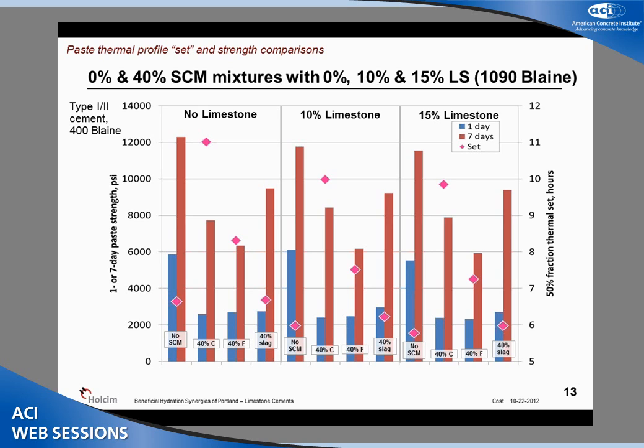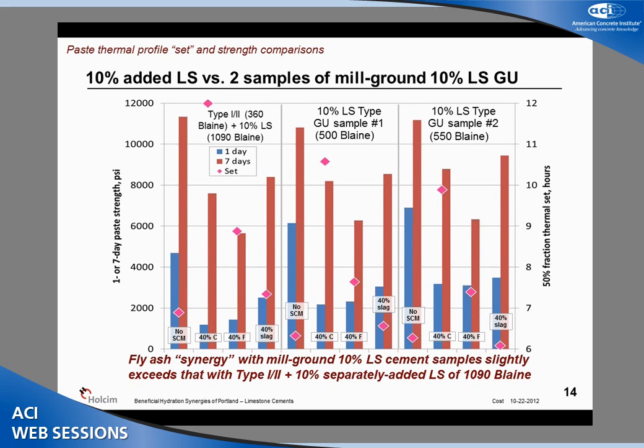Now, what was particularly interesting to me is when we took these sets of mixtures with 10% limestone of the finer grind that we had played with in the laboratory. We repeated this work with those same proportions and compared that to the performance of mill ground Portland limestone cements from our cement plant at the 10% level, theoretically the same material as we were attempting to simulate. The interesting thing is, and here's the system of the laboratory separately proportioned paste mixtures. Here is a 10% mill ground Portland limestone cement at about 500 meters square per kilogram Blaine. And here is a slightly finer, about a 550 meters square per kilogram Blaine limestone.